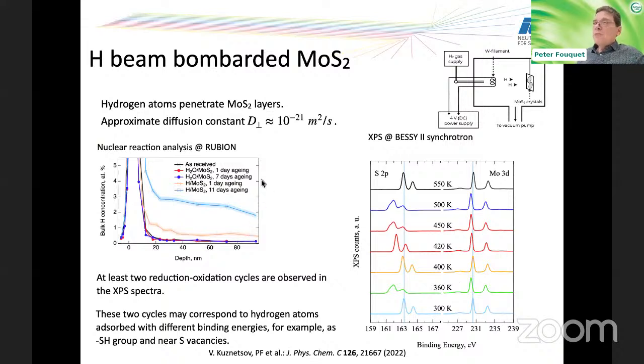In the hydrogen beam bombarded molybdenum sulfide, we saw a very nice penetration into this sample in nuclear reaction analysis. So here we see in deeper depth a substantial signal, and we saw some signal on the first day, but then even much stronger signal a few days later after aging. So there is quite substantial uptake of hydrogen on these samples and some slow diffusion process into this layered crystal after days. We also saw when we looked at XPS, heating up the sample, that there is reactivity. There's not much happening on the molybdenum line, but the hydrogen seems to be strongly bound to the sulfur, and there's chemistry happening there.